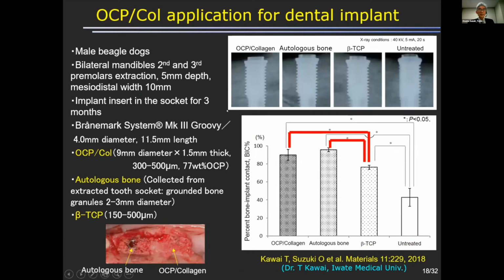This is an experiment using a beagle dog conducted by Dr. Tadashi Kawai of Iwate Medical University and published in Materials. And after the extraction of the tooth, the implant was inserted into the defect, and also the autologous bone and commercially available beta TCP granules were implanted around the implant.